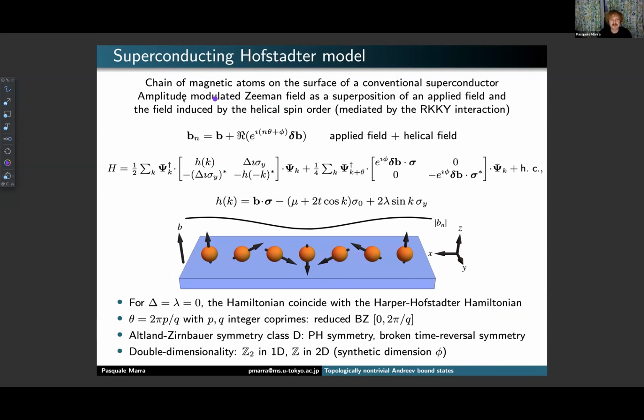And one can have an amplitude modulated Zeeman field, because one can have a superposition of a helical spin texture, so the magnetic field induced by the helical spin texture, and one can apply an external field coplanar with this helical chain. In this case, one will have a magnetic field which is periodic in space and also has a non-uniform intensity. So basically, if one can switch off the superconducting pairing and also the spin-orbit coupling, this Hamiltonian is equivalent to a Harper-Hofstadter Hamiltonian, which has been studied in the context of the Thouless pump and quantum Hall effect.